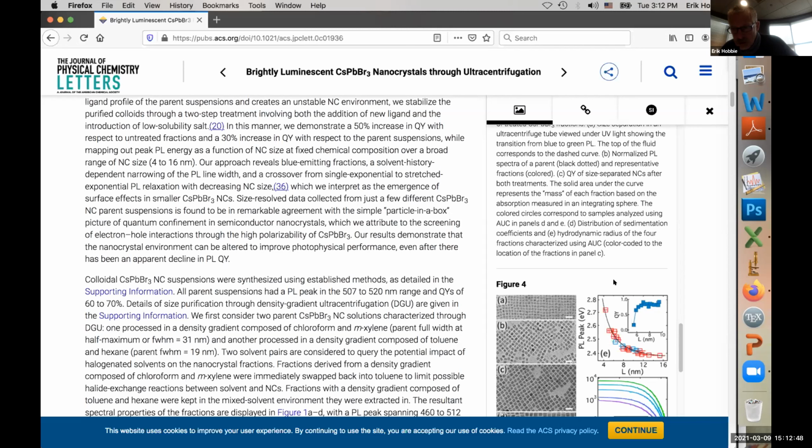Is that right, Aaron? Yeah, it's bigger because it has a lower dielectric constant. I think the number I usually see thrown around is like 5 nanometers. Well, this isn't too far off that. It looks like right at about 6 is where you get above 8 and you're definitely starting to flatline, right? Yeah, and those numbers, I think those are just straight from effective mass, so they're fairly crude for perovskites because it doesn't include the additional dielectric.